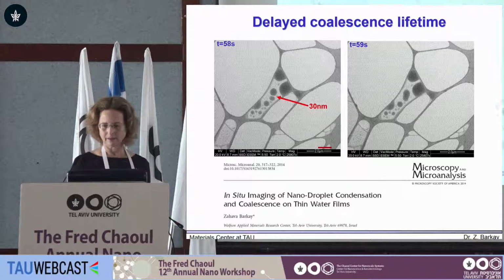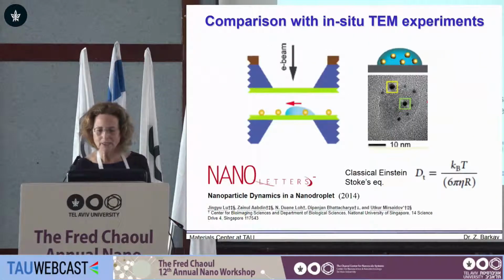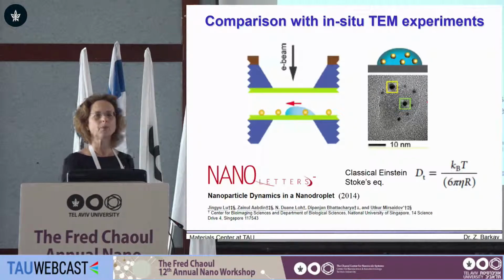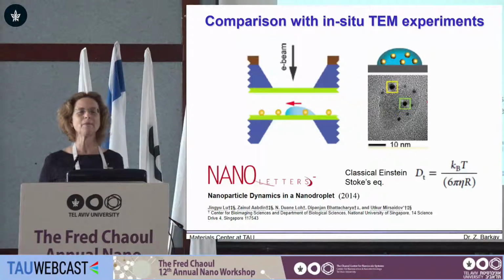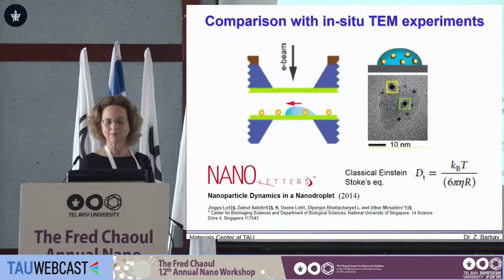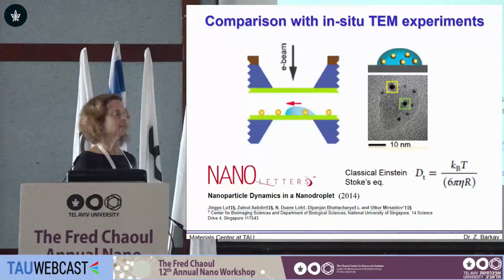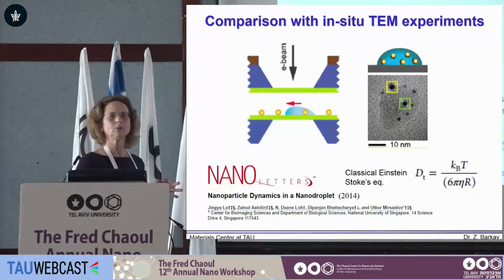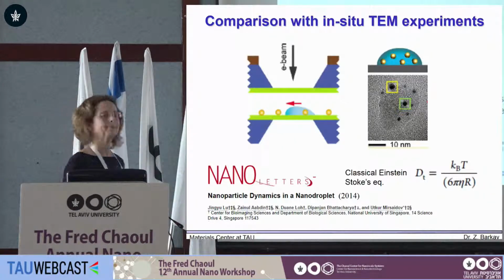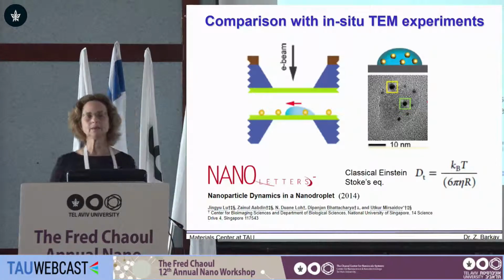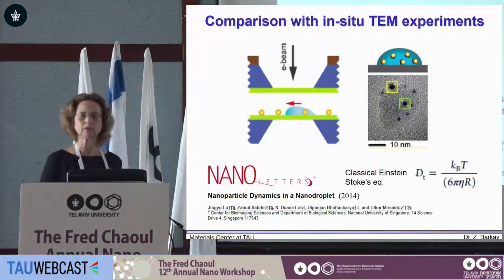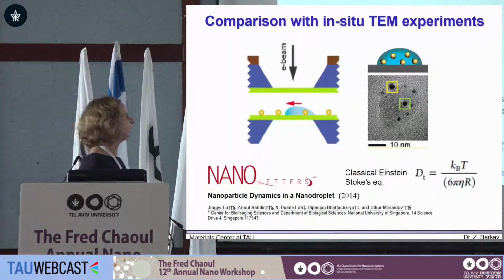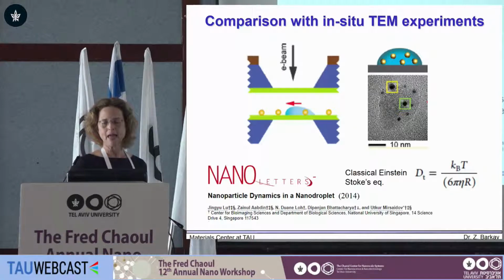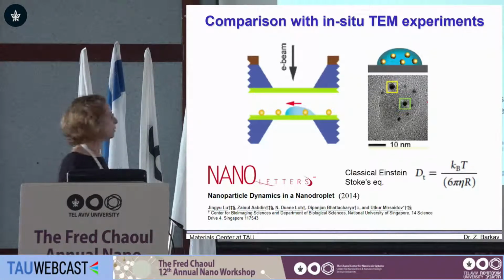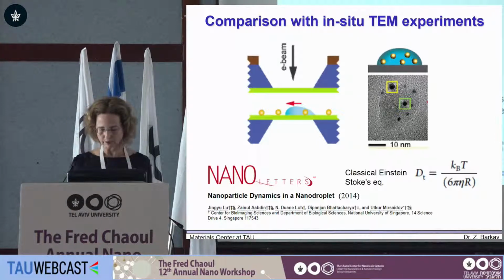In Singapore, at the National University of Singapore, they were performing very similar experiments, but in a different setup. They used the window technique, and put a very thin drop - you see the scale here - and inside they put some nanometer gold particles. They measured the movement of these gold particles, and according to time scales and distances, they concluded that the diffusion constant is very, very small. They talked about very high viscosity, and finally concluded that there is also pinning to the substrate. So the conclusion was very much similar.